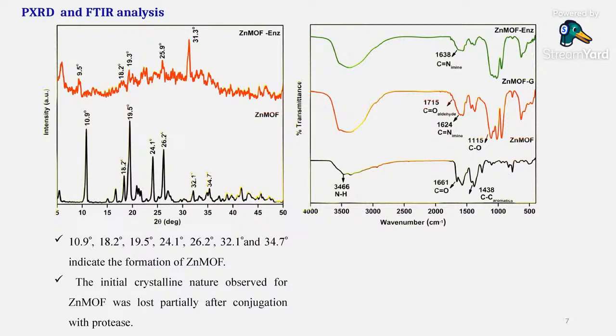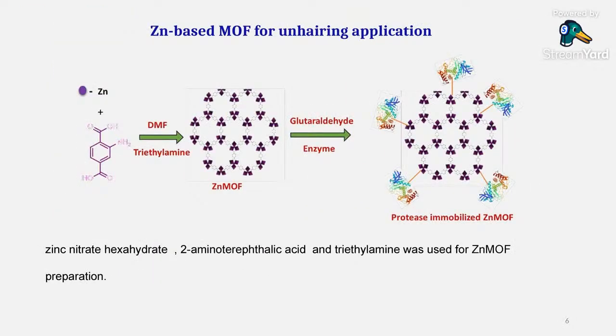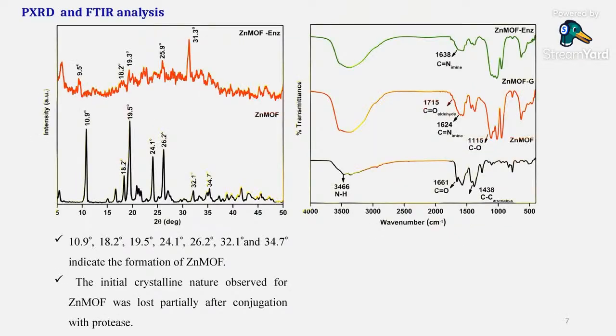Before going for any biological studies, we have to characterize the material: how good it is, what kind of pattern it has, whether the immobilization takes place. Everything we have to monitor. So we prepared the zinc MOF, and we have to use different techniques to understand the coating of the enzyme, the immobilization of the enzyme on the MOF. So we did the powder XRD. When we did the powder XRD, the zinc MOF gives a very nice crystalline pattern. How will you differentiate the crystalline from the amorphous in the powder XRD?